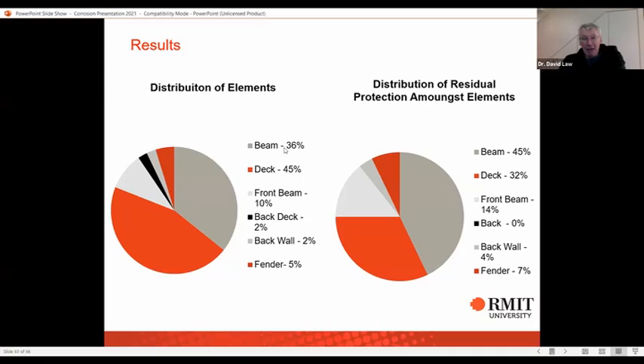So the elements that we were able to look at, 36 were beam. Out of the elements that actually showed residual protection, slightly more of the beam showed residual protection than the deck did. But overall, there was nothing much other than the fact that the back deck failed and didn't show any protection at all.